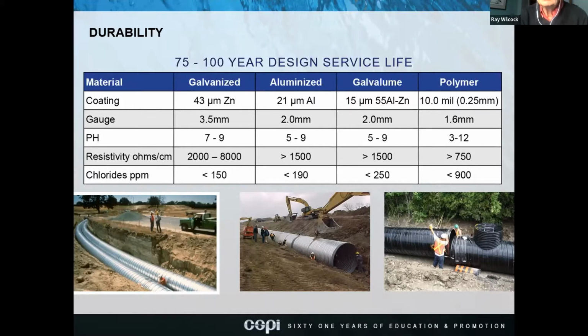And then resistivity, same thing. 2,000 to 8,000 ohm centimeter for galvanized, and then going across the board, you'll see that the other coatings perform much better in lower resistivities. And chlorides are in parts per million. These are basically salts, but they can be a number of things that run off. And you can see polymer will even perform in greater than, almost up to 900 parts per million,